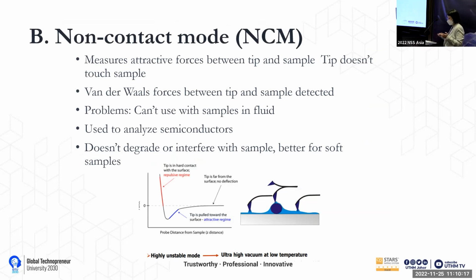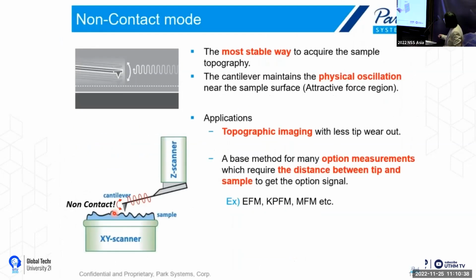So it's a good measurement mode because it is not contacting the sample. However, it's not advisable to use with a liquid sample, which will give you artifacts. We've tried before. We tried to challenge this AFM system to measure in fluid, but the buoyancy of the fluid will affect the measurement. Okay, so I skip this one.